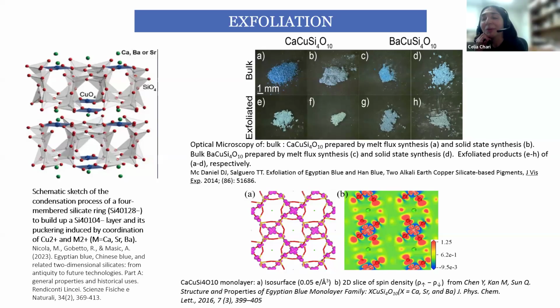The idea is that they start with ceramic technology, then they move to coating of, for instance, stone also. So they were able to make a coating, a glassy coating, a vitreous coating, like a glaze of a stone. Then they move to faience, that is similar to glaze. Then from faience, they move to Egyptian blue when you arrive at a certain ratio between the raw materials.